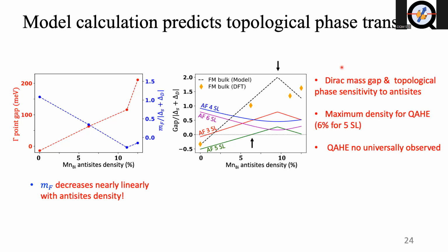Okay, so a short summary from this calculation result. We can see that both the Dirac mass gap and topological phase are quite sensitive to the anti-sites. And we made a prediction for the maximum density in order to observe the quantum anomalous effect. Above 6% is no longer a topological phase, so you will not expect any quantum anomalous effect. And we think this provides an answer for why the quantum anomalous effect is not universally observed in the field.